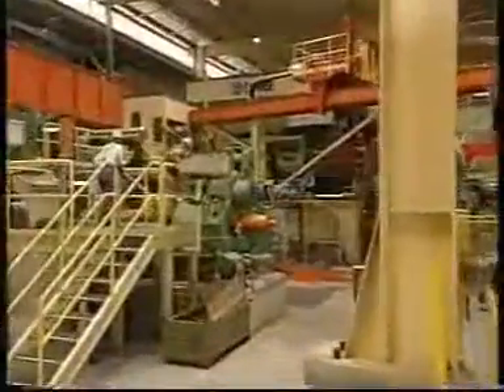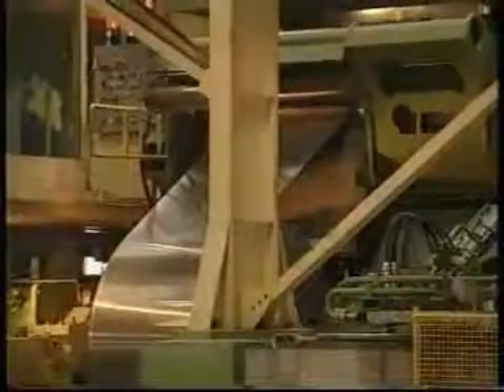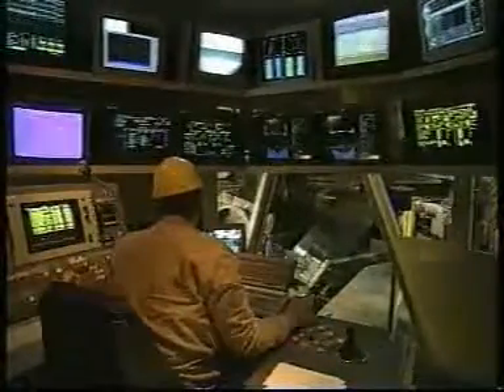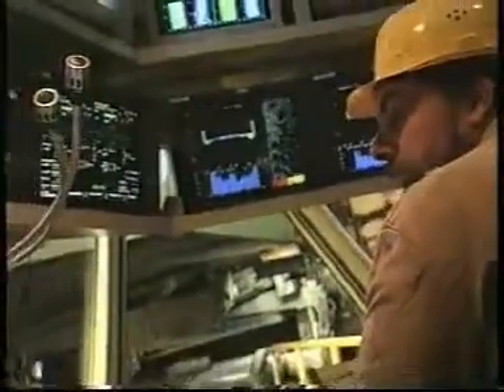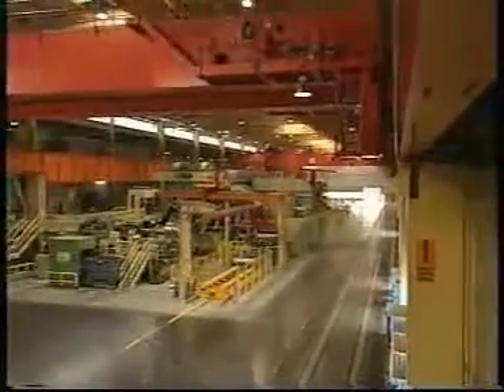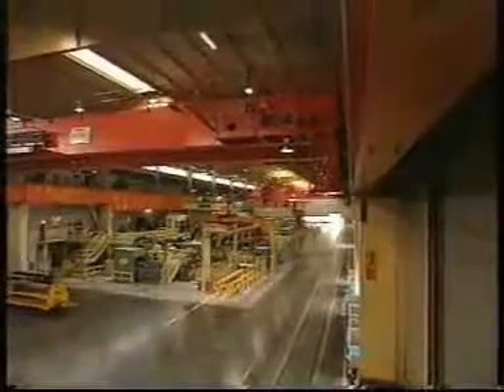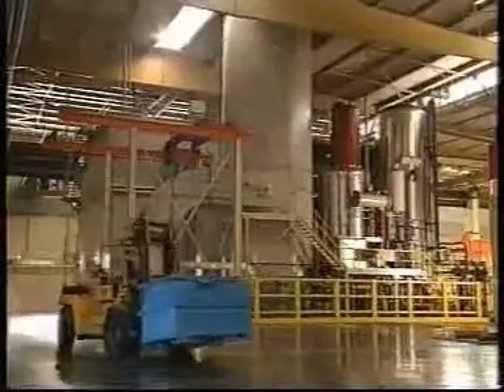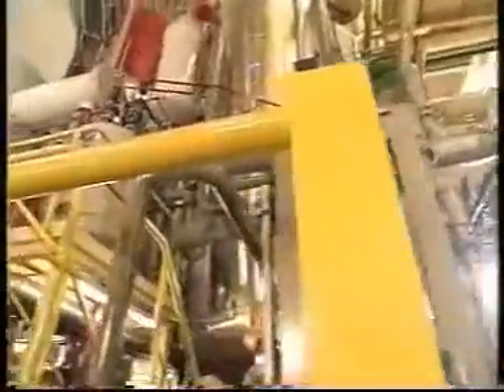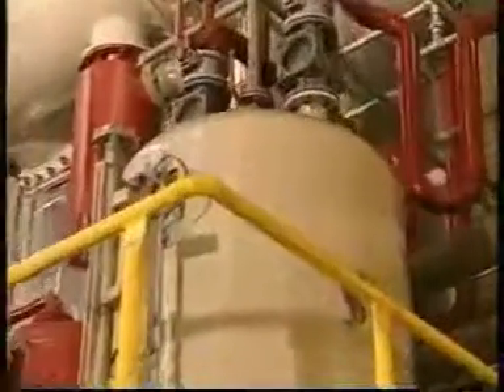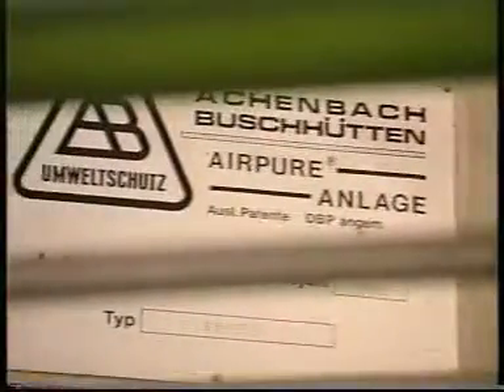On these mills, the hot mill coils are cold rolled to gauges of 0.2mm to 4mm in widths of up to 2,100mm. Speeds of up to 1,650 meters per minute are reached. Automation systems and numerous aids guarantee a consistently high quality level at all stages of production. The air exhausted from the mills is cleaned of rolling oil by passing it through an extensive system of scrubbers. These air-pure systems are a worldwide patent and meet the strictest environmental standards.